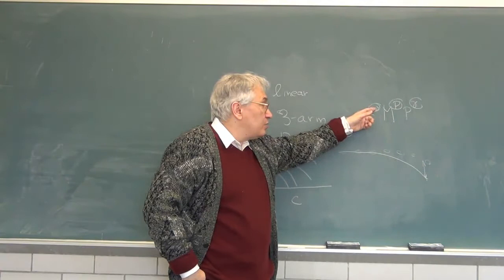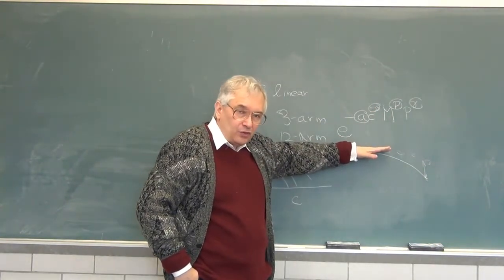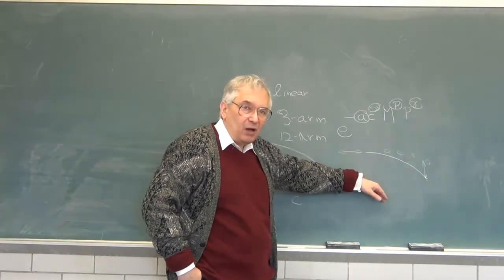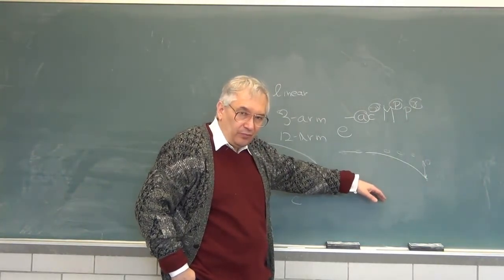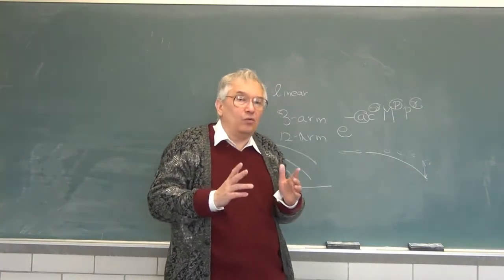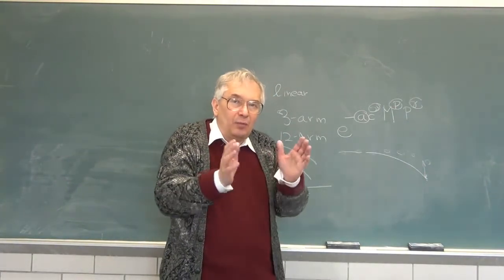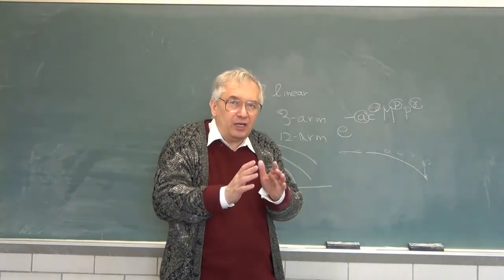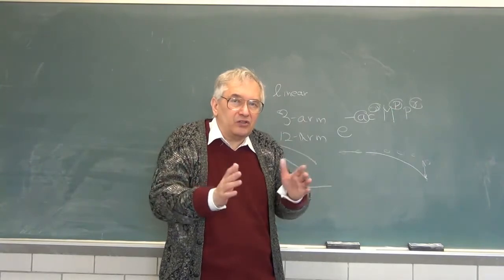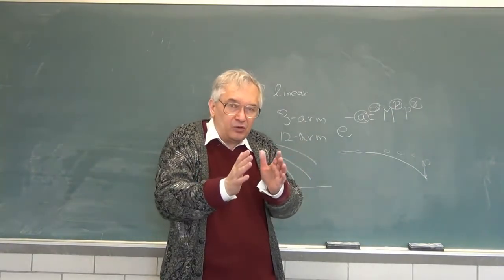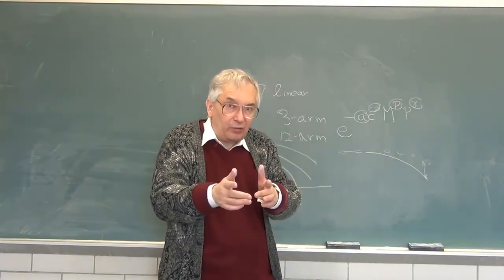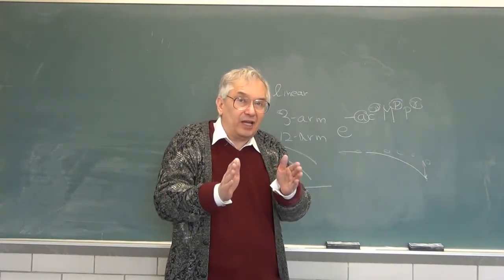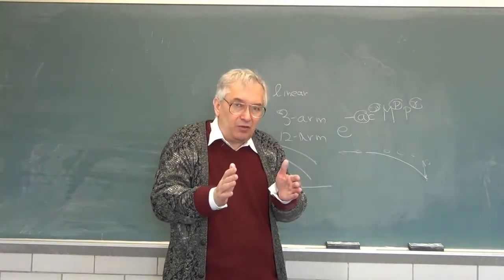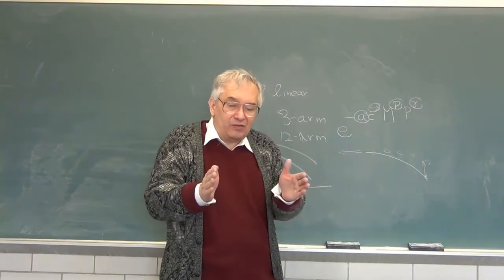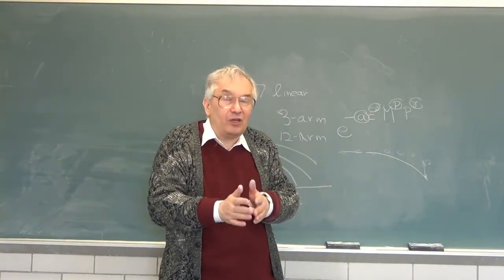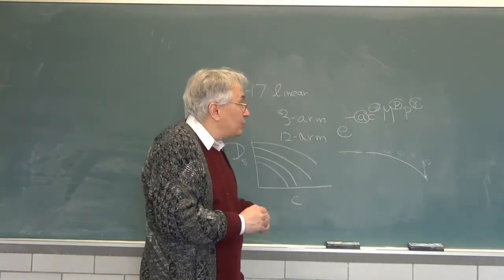And the concentration exponent starts very near 1 for small polymers and heads down towards about half for large polymers. The reason for this, one proposes, is that small polymers do not change their radius of gyration very much as you increase the concentration of the matrix, but large polymers contract, and we saw that with dielectric relaxation, where small polymers by direct measurement did not contract as you ran up the matrix concentration, but large polymers very definitely did go to smaller radius, and we could actually describe that quantitatively. That was in an earlier lecture.